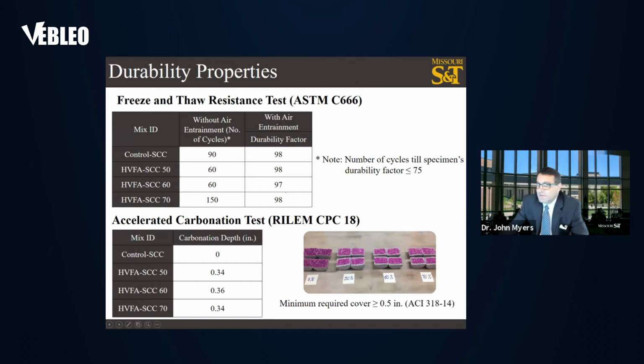In addition, to look at the durability performance, the freeze and thaw resistance test was evaluated. And for all of these mixes, they provided very excellent durability behavior. With an air entrainment admixture, the targeted durability factor of 75 was well exceeded.